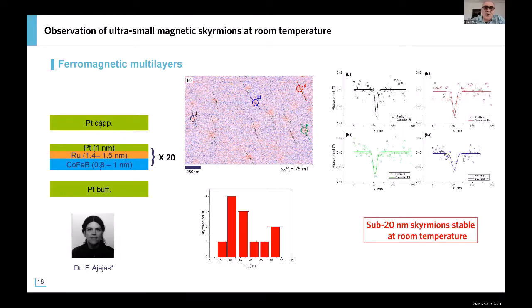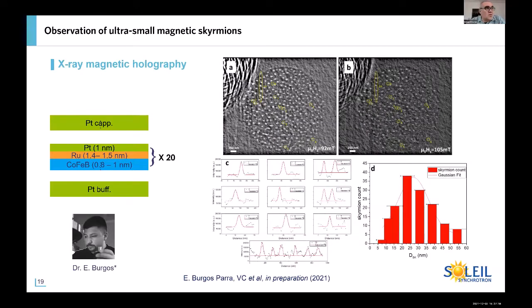But then using MFM, there is always the question about the interaction with the tip, that is magnetic itself. And this is why in the postdoc of Eric Burgos, in collaboration with Synchrotron Soleil, we use this technique that is called X-ray magnetic holography, preparing the very same sample, but on membrane, and shining coherent X-rays on these membranes. We can have an image in transmission first, and we can make a statistic on a very large number of skyrmions without perturbation from the tip like in MFM. And from this, we also have a statistic, and you see that again, like in MFM, it means that the MFM image was not perturbed that much by the tip. We have a diameter that is about 20 nanometer on average.